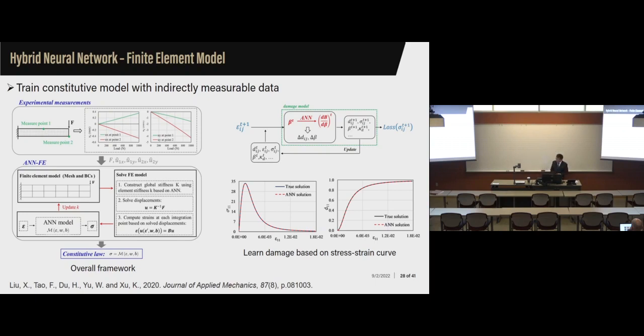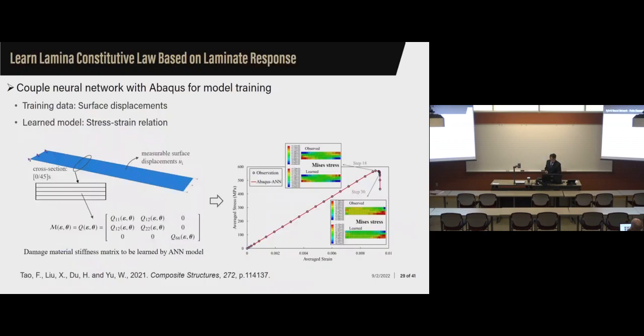We actually found we can very accurately learn the nonlinear behavior for the constitutive models. It's not just model calibration, where you have an assumed model and get some parameters. You actually learn the model itself, how the curve should behave, the stress-strain curve. And the second part is how the damage progresses in terms of the strain. When you know your strain, then you can figure out the corresponding D11, which is damage along the axial direction. And the last is to learn the damage law. And you'll find we can simulate the nonlinear curve and figure out where it will be damaged.